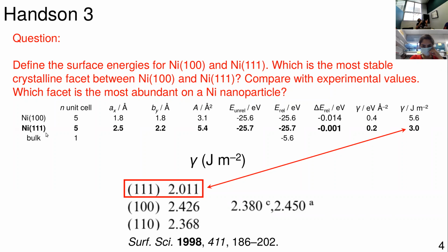If they have XRD characterization, then it's perfect, because you can directly say, look, they see experimentally 111, 100, so I model 111, 100. But in case you don't have XRD, then the way is instead to say, look, I calculate 111 is the lowest energy configuration according to the Wulff theorem. That means that it is the facet that is the most abundant, and so you just say, look, this is the value. Okay, so just for you to remember that part, because you may have to apply that in your future, like according to the project video.